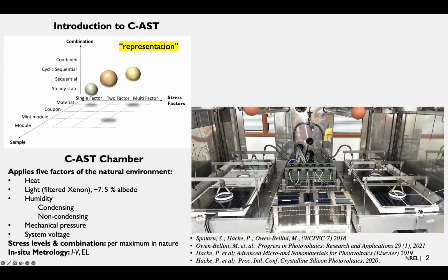The chamber, an image is shown here, and something to point out is that as it deals with bifacial modules, we have aluminum reflecting troughs here, which send about 7 to 8% of the illumination in the UV range. Well, full spectrum, but we're mostly concerned about UV with respect to reliability and durability. These aluminum troughs reflect light to the backside of the module.